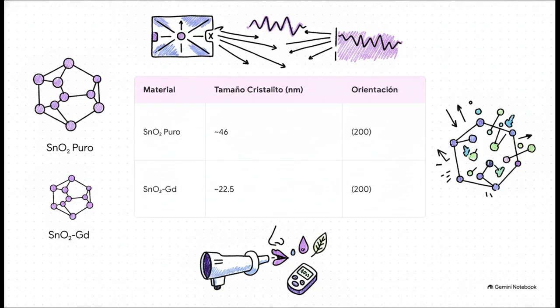But here's the really cool part. The gadolinium doping caused a massive drop in crystallite size. We went from roughly 46 nanometers in the pure samples down to about 22.5 nanometers in the doped ones. Shrinking the crystals like this is huge because it drives up structural defects and lattice strain, which, as you know, is exactly what you want if you're trying to trap gas molecules.